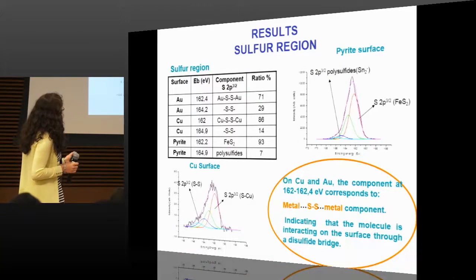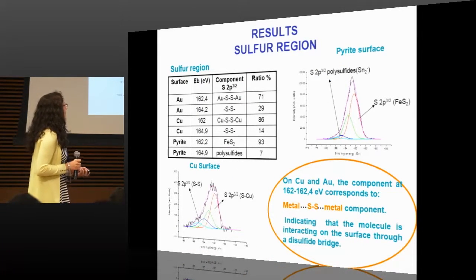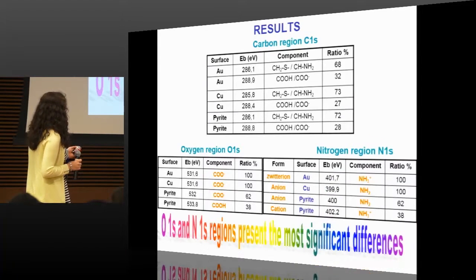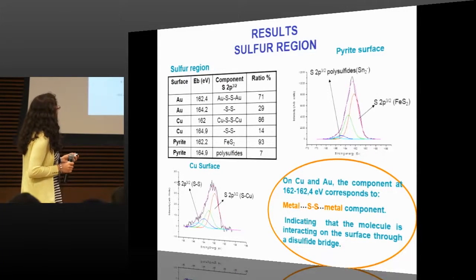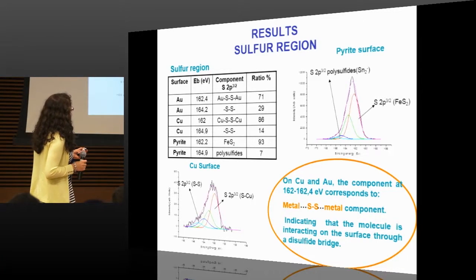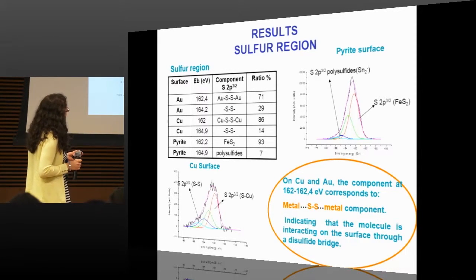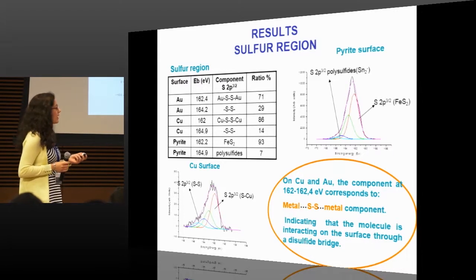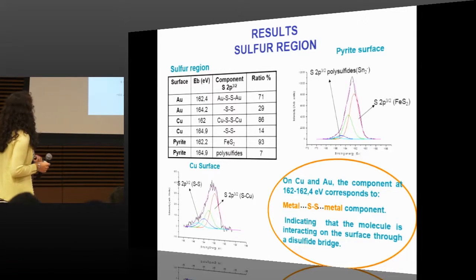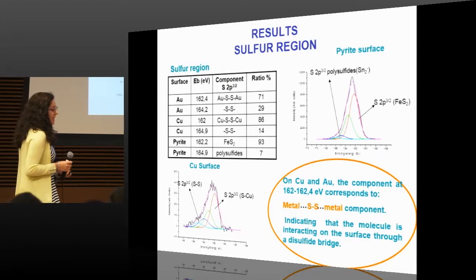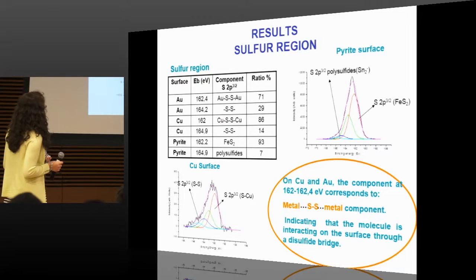And about the sulfur region, on the pyrite surface, we have two components too. The main component is the disulfide iron of the natural pyrite, and the other component is polysulfide present in the natural pyrite. And on copper and gold surface, I have similar XPS spectra, and I have two components.